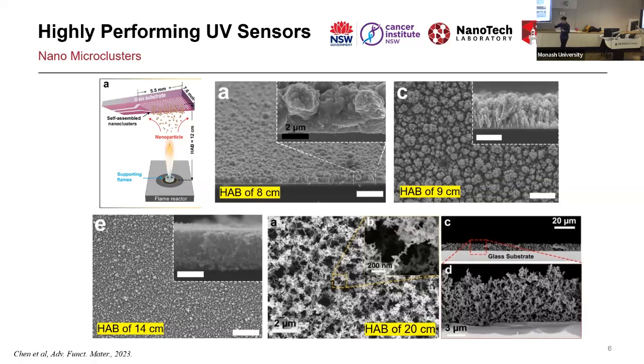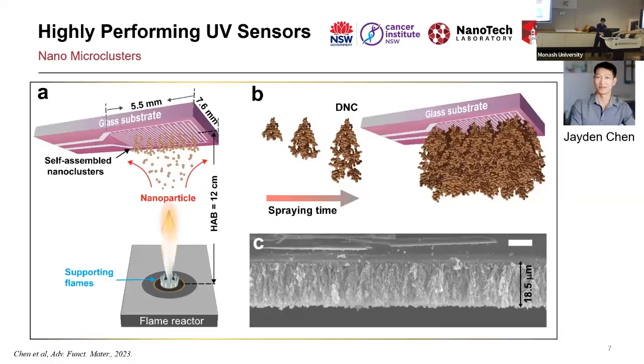So for some sensing applications, you might prefer a bit higher height above the burner because it gives you way more porosity. But if you dip this one into the water, the film will collapse because it's not strong enough. If you need something that should handle a little bit harsher environment, then maybe you would consider a bit lower height above the burner. But this is just one of the parameters that we can change. There is a significant number of parameters: the pressure of oxygen, the concentration of the liquid, the feeding rate of the liquid, and it's a completely different structure every time. You can literally create a wide range of structures just by changing each of these parameters.